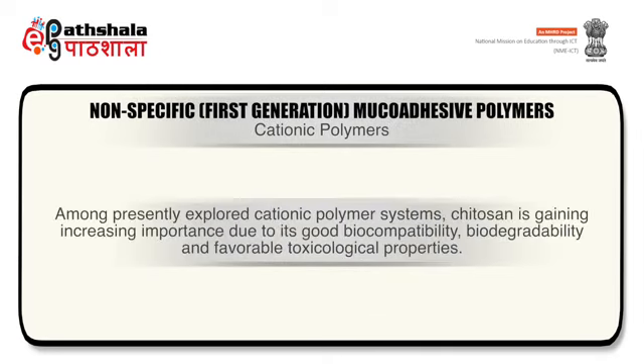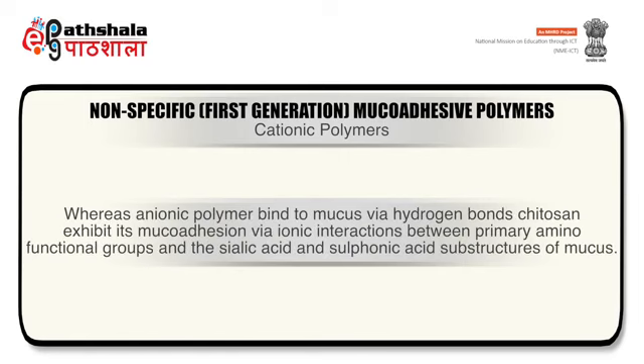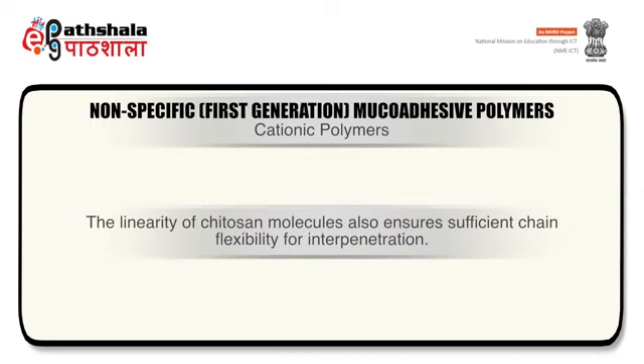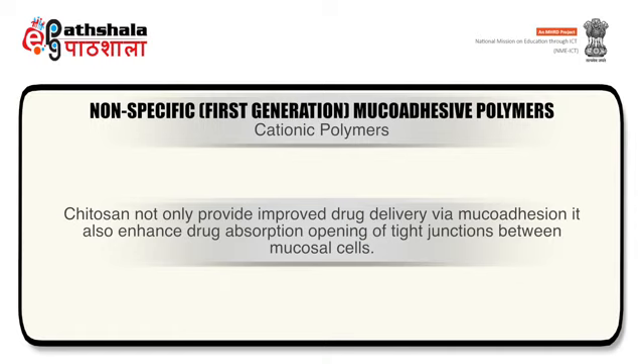Among presently explored cationic polymer systems, chitosan has gained increasing importance due to its good biocompatibility, biodegradability, and favorable toxicological properties. Whereas anionic polymers bind to mucus via hydrogen bonds, cationic chitosan exhibits its mucoadhesion via ionic interactions between primary amino functional groups and the sialic acid and sulfonic acid substructures of mucus. The linearity of chitosan molecules also ensures sufficient chain flexibility for interpenetration. Chitosan not only provides improved drug delivery via mucoadhesion, it also enhances drug absorption by opening of tight junctions between mucosal cells.